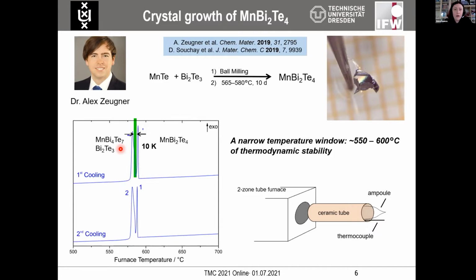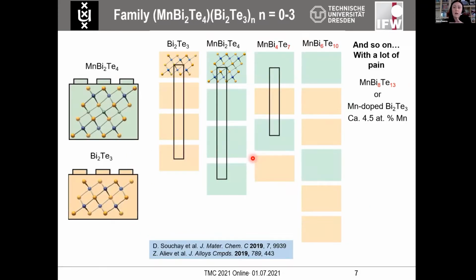So that means that if you are a materials researcher who wants to grow a crystal of this phase of a sizable size, you can only cool down the melts in this very small region between the crystallization peaks, which also entails very precise control of the synthetic temperature. And may I tell you, in modern tube furnaces, there are very often fluctuations up to 10 degrees, despite the very good control of thermocouples. Therefore, you need a whole array of these thermocouples next to your ampule to ensure that you don't cross this borderline. So if you played your cards right and you cool down your melt correctly, you may get nice crystals of these heterostructures, indeed ordered. So you will have a bulk periodic compound with defined crystallographic sites for bismuth and manganese.